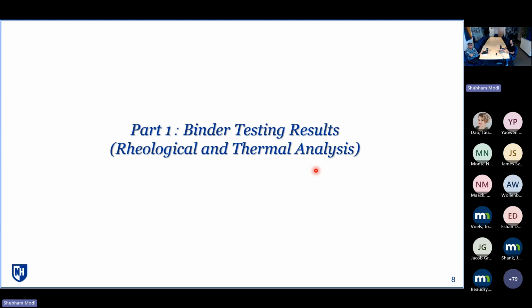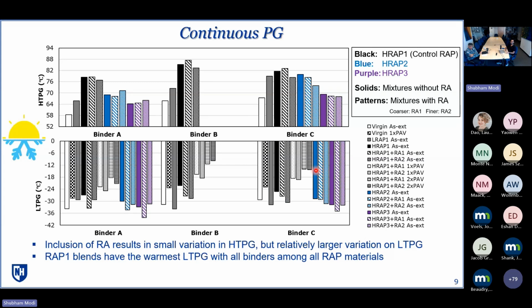We can now go through the binder testing results that cover rheological and thermal analysis. We started with the PG evaluation of the binder blends. Before we go into results, I want to go through the color scheme of these charts. The black color shows the high RAP 1, which was our control RAP as well, and the gray one shows the low RAP; here the RAP source is the same. The blue one shows the RAP 2 source, whereas the purple one shows the RAP 3 source. The solids are without any recycling agents, and patterns have recycling agents, where the coarser pattern shows the use of RA1, whereas the RA2 blends are shown with the finer patterns.